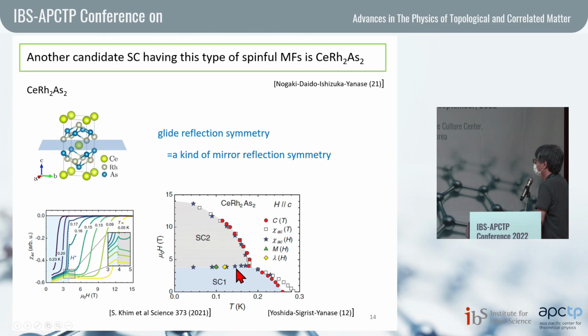And here I show the experimentally obtained phase diagram of the system. This is temperature, and this is the magnetic field in the z direction. This magnetic field does not break the glide reflection symmetries. According to the theory by Yoshida-san, Sigrist-san and Yanase-san, they predict two superconducting phases, a low field superconducting phase and a high field superconducting phase. They predict that the low field phase realizes an even parity superconducting state, and the high field phase realizes an odd parity superconducting phase. In more detail, they also predict that the low field phase is a glide even superconducting state, and the high field phase is a glide odd superconducting phase. So they predict these two phases.